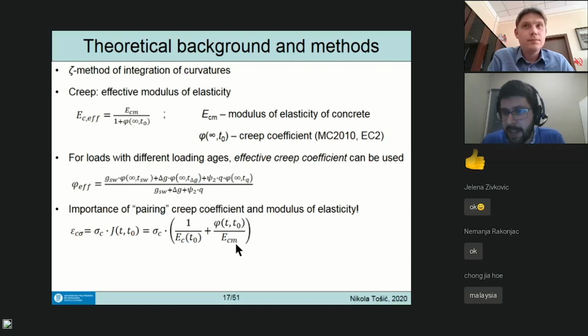So when you're using that, you should always combine it with the 28-day modulus of elasticity. That's important because your experimental creep coefficient, for example, would just be creep strain divided by initial strain, and it would be different. Your experimental creep coefficient would here also have the modulus of elasticity at T0. For example, the ACI formulation in the 209 model for creep uses the same modulus of elasticity. So it's wrong to take a creep coefficient calculated by ACI and plug it into a compliance that is from model code.